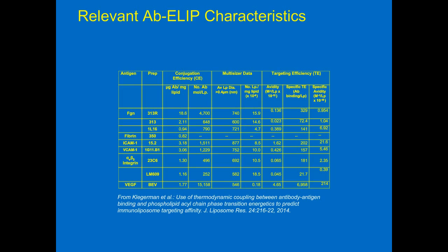Now, in terms of standardizing this assay, this is the trick. If you can access the slides, then you can see what the reference is. We had to use radiotracer methods. In other words, we did a conjugation of the liposomes with a radio-labeled IgG. And then we used that to come up with a primary standard of exactly how much IgG was on the liposomes. And then from there you can make secondary standards.